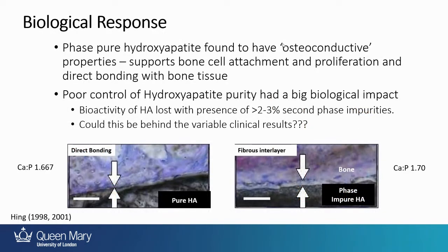So one of the things we did early on is look at what happens if we mess up our control of hydroxyapatite chemistry. We had made up some materials that were phase pure, so they had the magic calcium to phosphorus ratio of 1.667. And we made some that were a little bit calcium rich, with a calcium to phosphorus ratio of 1.7. So this was now phase impure, so it was mostly hydroxyapatite, and it had only 2% of calcium oxide in there as well. But that small amount of calcium oxide was enough to stop the material from being bioactive.